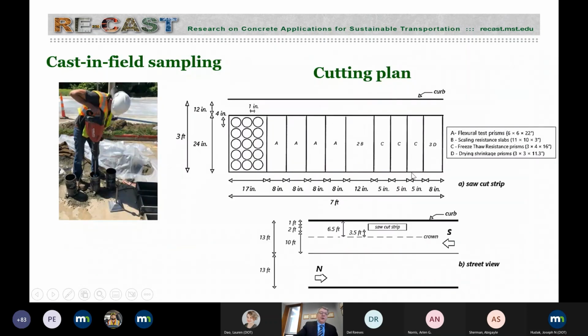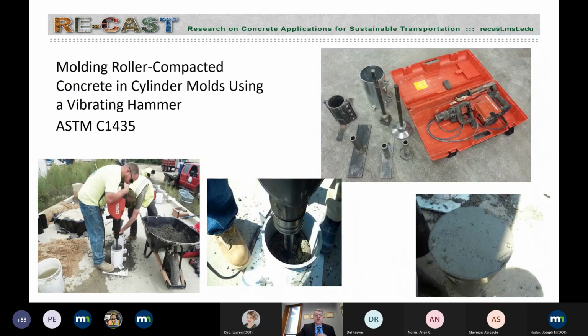So at Missouri S&T, we worked with MoDOT to take many samples. We took samples that were used for compressive strengths and elastic modulus, and took some prisms also to evaluate flexural strength. So the prisms are 6 by 6 by 22 inches. Scaling resistance, the icing salt scaling, freezing and thawing, as well as drying shrinkage. So all these samples were taken to the lab and moist cured in lime saturated water up to 220 days. And in terms of shrinkage, they were moist cured for 7 days and then left to air dry.